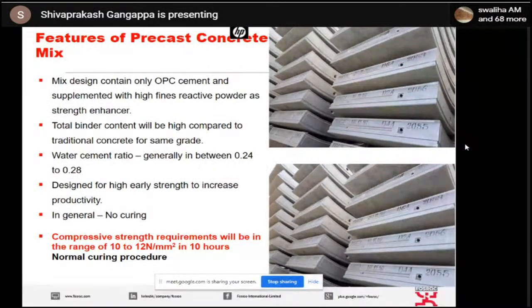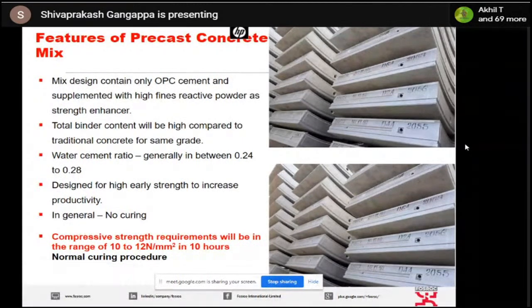So how can we achieve this? We already know that the moment we keep reducing the water cement ratio, the concrete becomes very sticky in nature. So how can we overcome this problem? Is it really practically possible to operate a concrete at 0.24 or 0.28 water cement ratio? We can produce such a concrete at laboratory level. Even in laboratory there are cases where we have gone up to 0.16. With 0.16, practically, is it possible for us to deliver the concrete at the site with retention and a higher strength parameter?